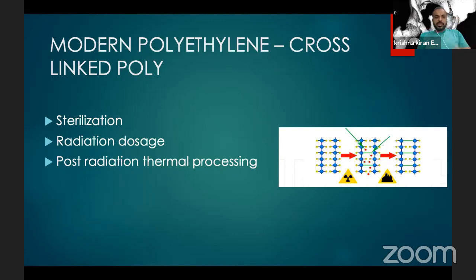So the important consideration here is the radiation dosage. You have moderately cross-linked polys where the radiation dose is between 5 and 7.5 megarads. If you have more than 7.5 and up to 10, then you have a highly cross-linked polyethylene, which is available. Most of the implant companies have highly cross-linked polyethylene now, and this is a standard of care in choosing a polyethylene bearing in total hip arthroplasty.